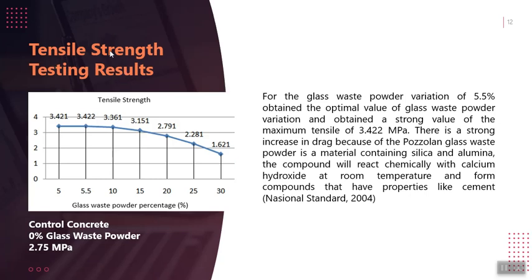And then these are the tensile strength testing results. The glass-based powder variation of 5.5% obtains the optimal value and the maximum tensile strength of 3.422 megapascal.